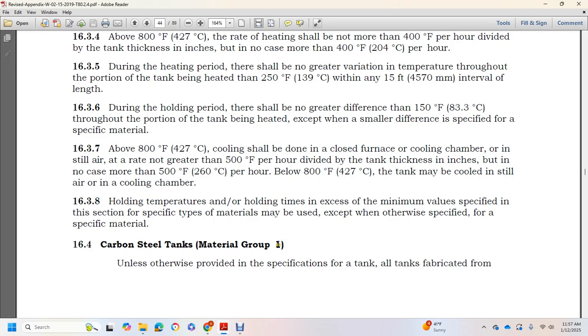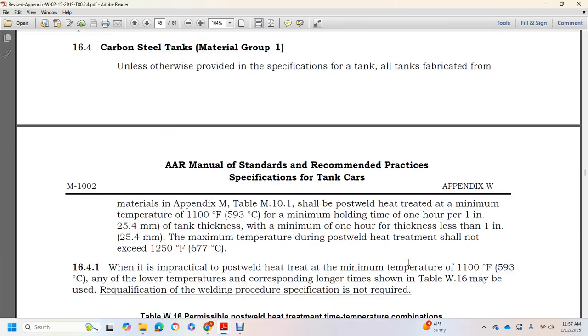Carbon steel tanks, material group 1. Unless otherwise provided in the specification of the tank, all tanks fabricated from materials in Appendix M, Table M10-1, shall be post-weld heat treated at a minimum temperature of 1100 degrees Fahrenheit with a minimum hold time of 1 hour per 1 inch of tank thickness. The minimum hold time is 1 hour for thickness less than 1 inch. Maximum temperature during post-weld heat treatment should not exceed 1250 degrees.